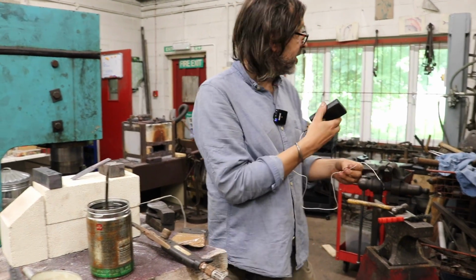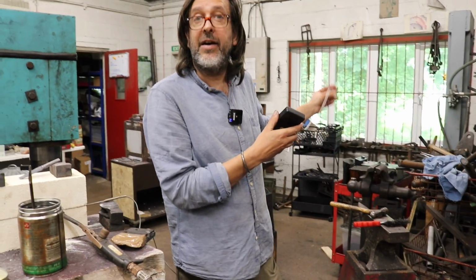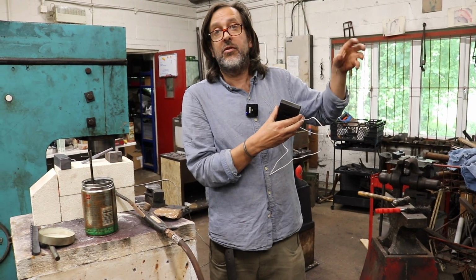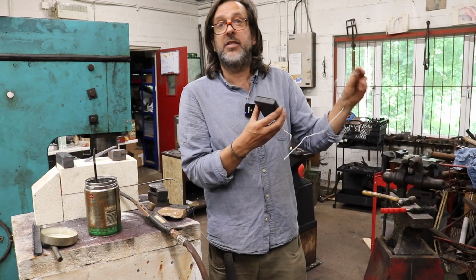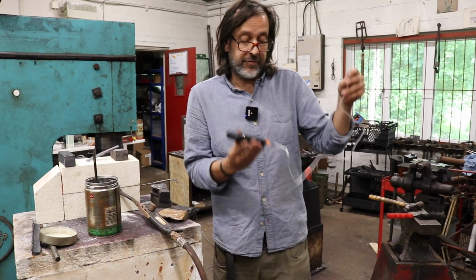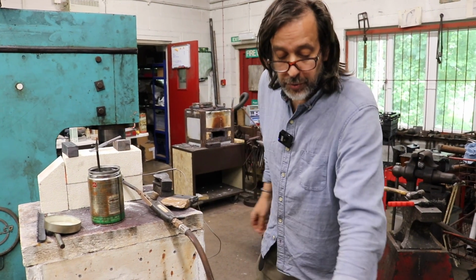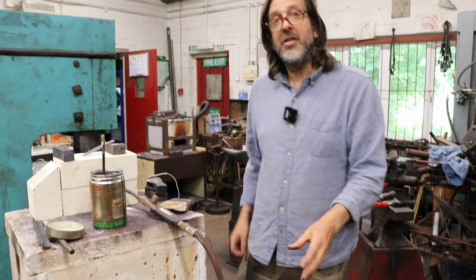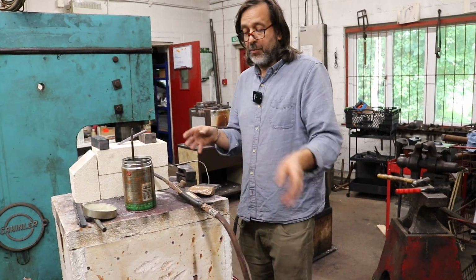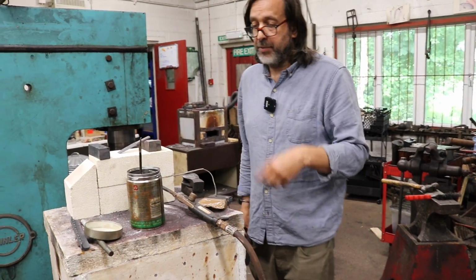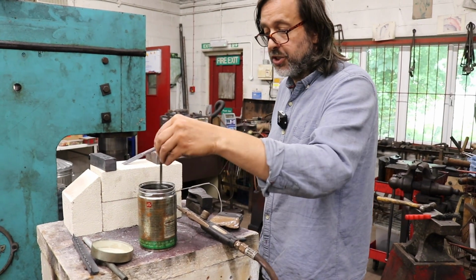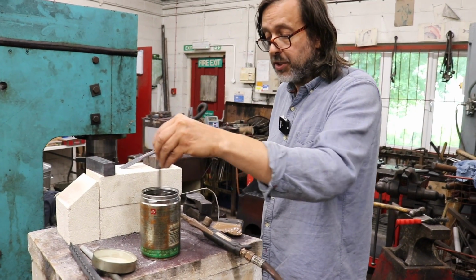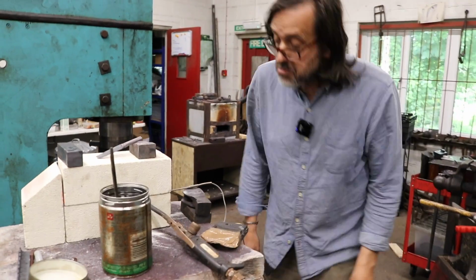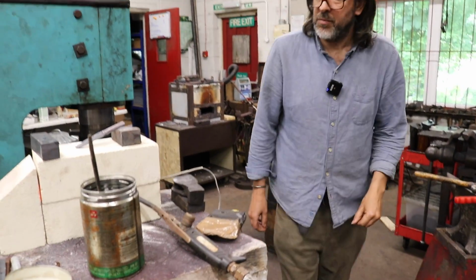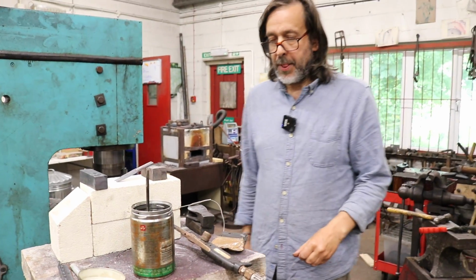We're going to be tempering with a deep fat fryer, and I could bung that in, or I have in the past bunged it in and checked that the temperature dial on the deep fat fryer actually equates to the temperature the oil's at. So you can use it for what you would normally think of as high temperature measuring, but in actual heat treat terms it won't take forge temperatures, but it's good for tempering and checking the temperature of quenchants.